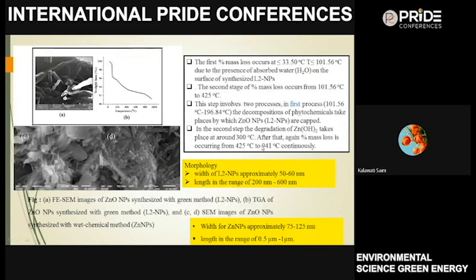In the last one, the degradation of zinc dihydroxide takes place around 300 degrees centigrade, and after that the remaining mass loss occurs from 425 degrees centigrade to 941 degrees centigrade, continuously. And at last, if we continue, we get only zinc metal if the thermogravimetry analysis is done in the presence of nitrogen gas. If it is done in the presence of air, then only zinc oxide remains.